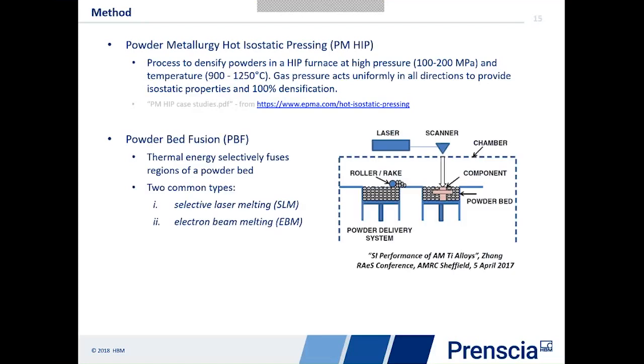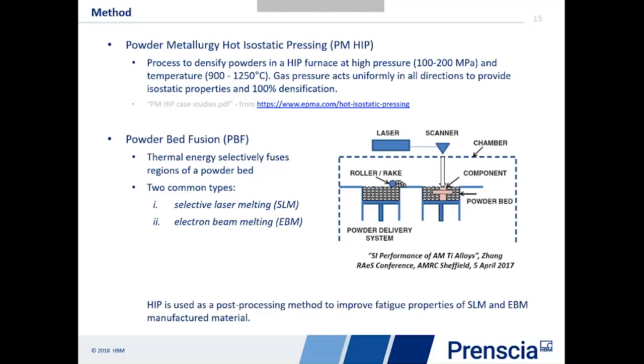The other thing we're looking at is powder bed fusion. This is where we use selective heating. Here's a little illustration of a typical process. We have a powder delivery system. This takes the powder and lays a thin layer, and then we use a laser or some form of heat to locally heat it and to create the component. And we're looking at two different scanners here, selective laser melting and electron beam melting.